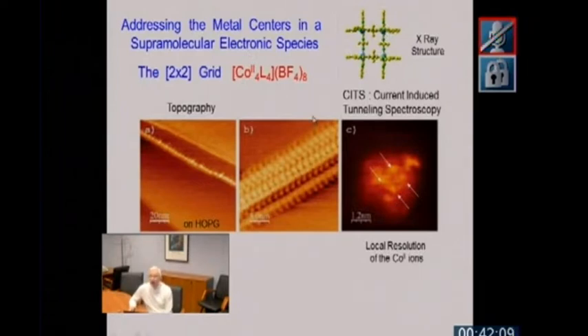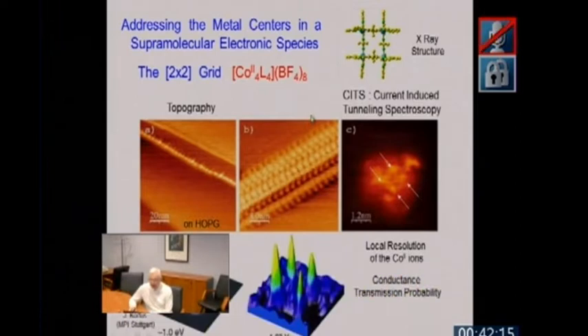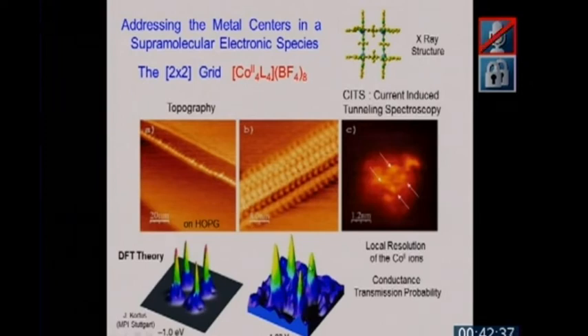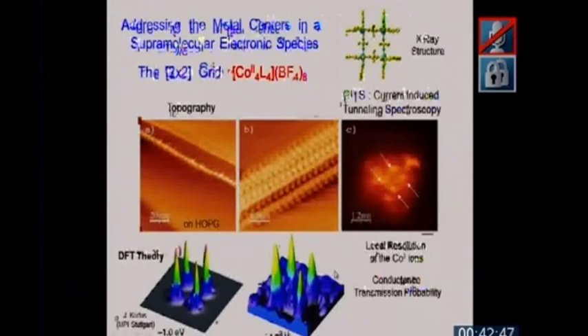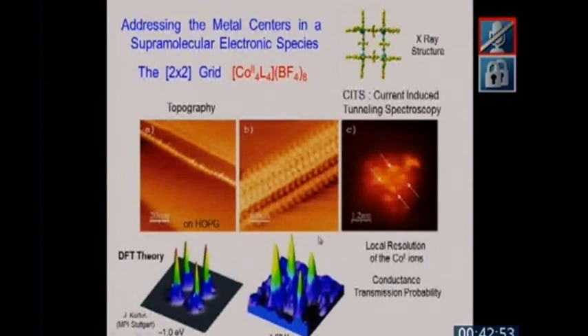If you look now at the current passing through the tip of the microscope, you see that when you pass over one of those cobalt centers, the current increases, conduction increases, meaning that more current flows, and therefore you can look at this as a way to talk with the cation. You see a large increase in current as you go exactly over these cobalt centers. So this is describing one stage, and of course one can then think of introducing different cations at different places and do a lot of different things, but I haven't time to get into all that.